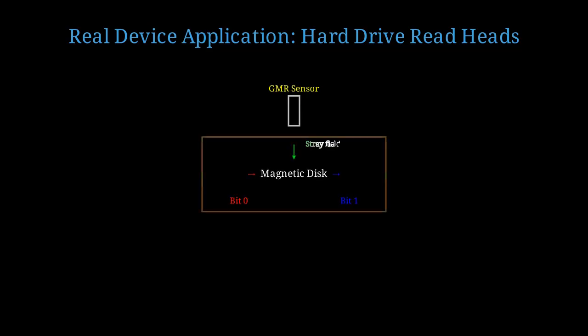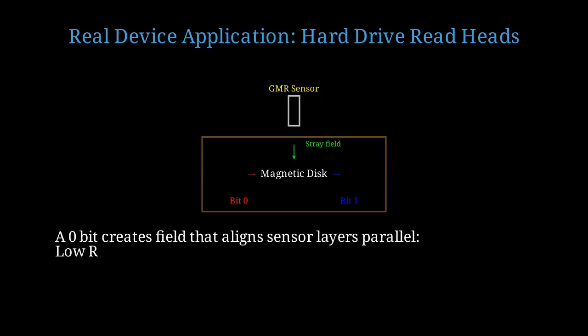Now let's discuss how GMR became a transformative device technology, revolutionizing data storage in hard disk drives. Here's how it works. A GMR sensor, only a few nanometers thick, flies just a few nanometers above a spinning magnetic disk. The disk contains microscopic magnetic domains representing bits of data. As different bits pass under the sensor, the stray magnetic field from each bit switches the sensor between high and low resistance states. When a 0 bit passes underneath, its magnetic field aligns the sensor layers parallel, giving low resistance and a low voltage signal.